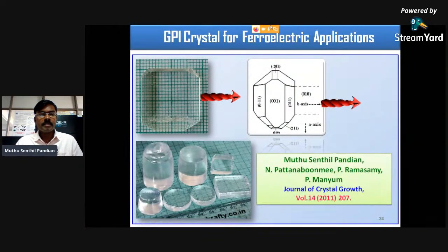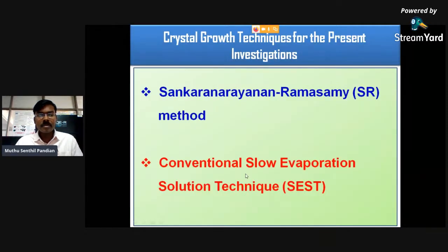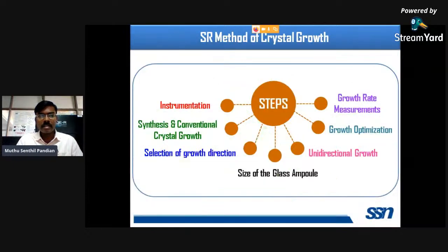Okay, these are the ferroelectric glycine phosphite single crystals grown by the conventional method. So we have selected this polar b axis for the unidirectional growth, and we have solved the structure. We have identified the polar b direction. We have mounted it at the bottom of the glass ampoule, and this is the crystal grown by the conventional method. These are the cut and polished wafers by the SR method. So the crystal growth techniques for the present investigation I am going to explain are this SR method, the Sankaranarayanan Ramasamy method, and the conventional slow evaporation technique.